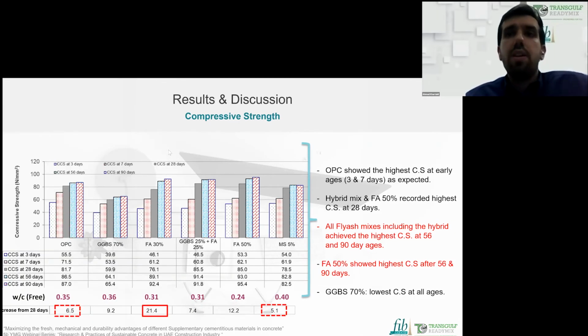Coming to the compressive strength, as mentioned earlier, since our concrete mixes had different water contents, we end up with different water cement ratios, so we definitely will end up with different strengths. But at the end, the target here is to maximize the benefit of the supplementary cementitious material. It can be noted that the highest strength achieved was for the 50% fly ash. I'm talking here about 90 days. Of course, it was evaluated at 28 days, 56 days, and 90 days.